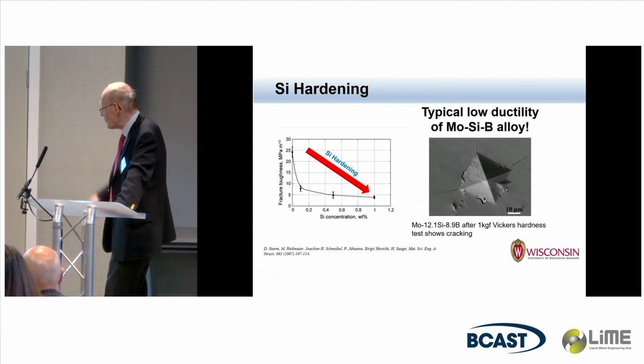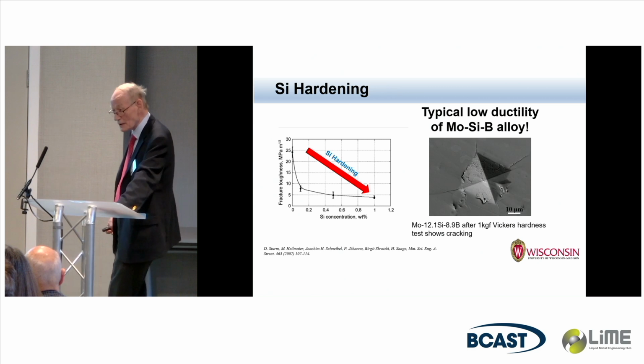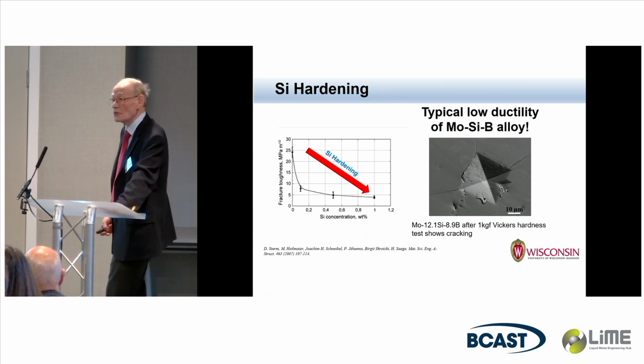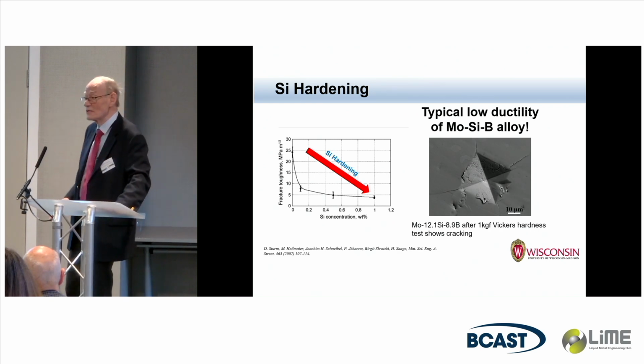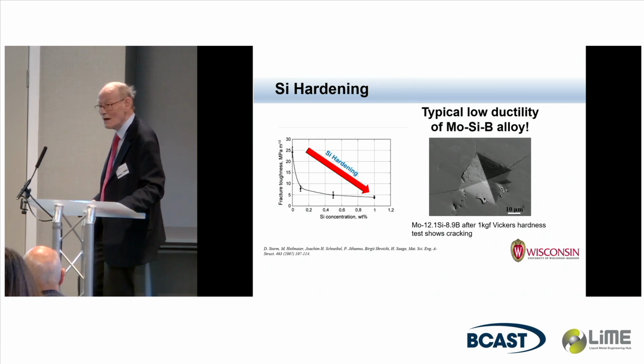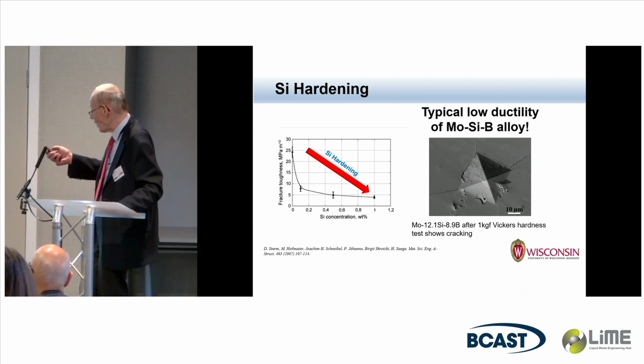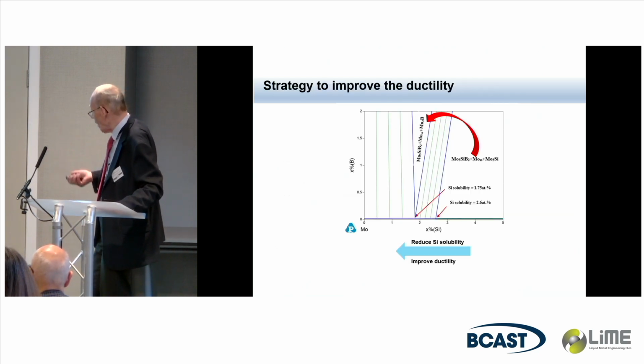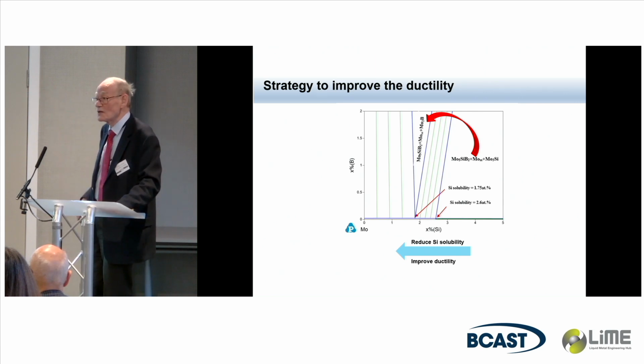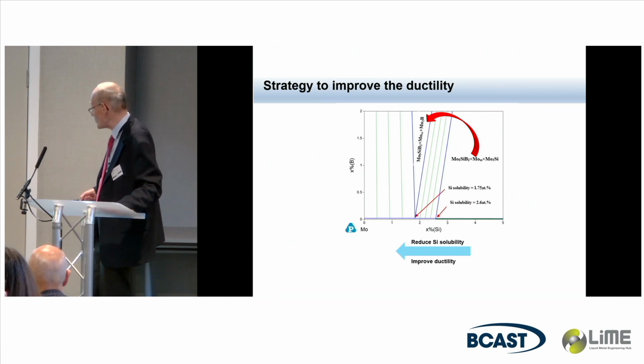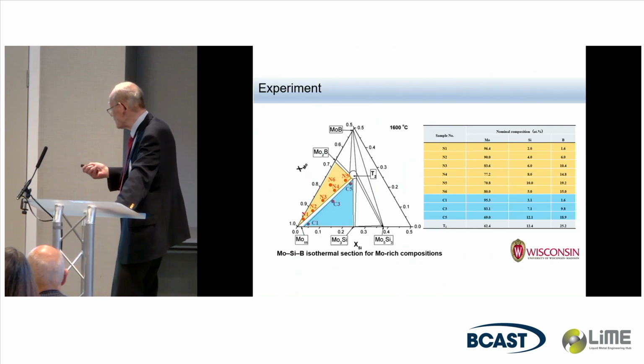And then we've looked at the literature, and there's reports that the problem with the molybdenum silicon boron is the silicon. Silicon is the most potent solid solution strengthener in molybdenum. We have too much strength, so we have to reduce the silicon content. But how do you do that when you have a guaranteed solubility? Well, we go to the other side of the phase diagram, which has much lower solubility. So we've reduced the solubility from 2.6 to 1.75, and that improved the ductility.